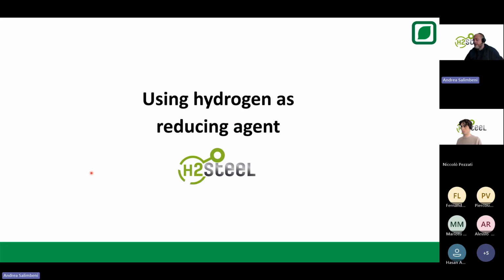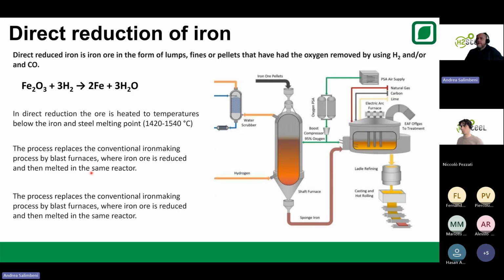So we discussed coal, but coal is not the only reducing agent. Hydrogen is becoming really interesting because it's a reducing agent that produces water vapor and not CO2 when it reacts. And that is why the direct reduction of iron is taking attention, and it is part of this project. What is direct reduction of iron? Direct reduction of iron means that we decouple the production of iron metal from the melting of the iron metal. In a blast furnace, the iron ore is simultaneously, we can say, reduced and melted, producing hot metal with carbon inside. In the direct reduction or pre-reduction of iron, we have iron ore which is injected in a reactor staying at likely 900 degrees, so much lower than the iron melting point.